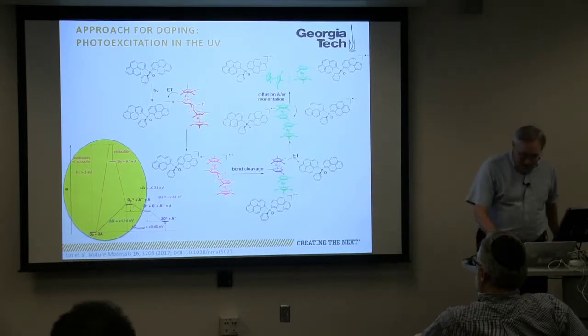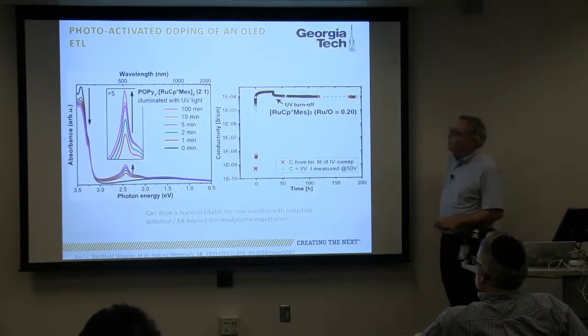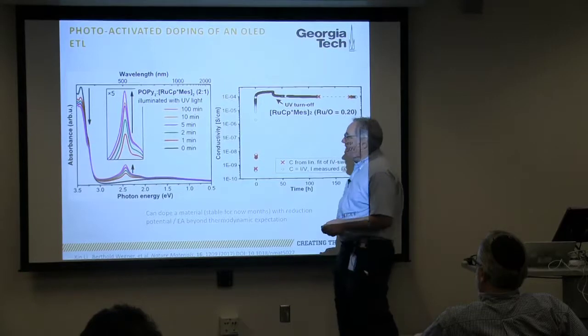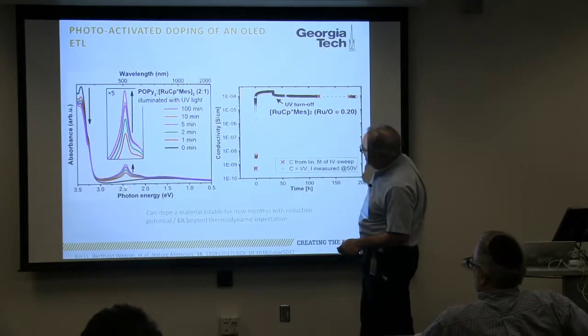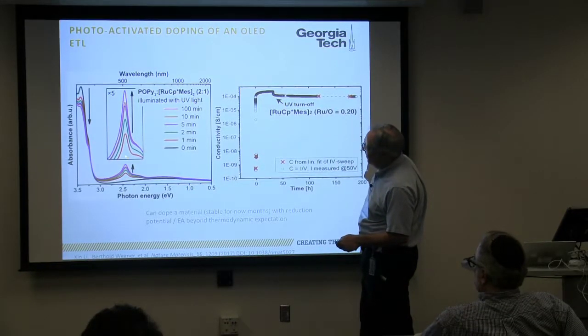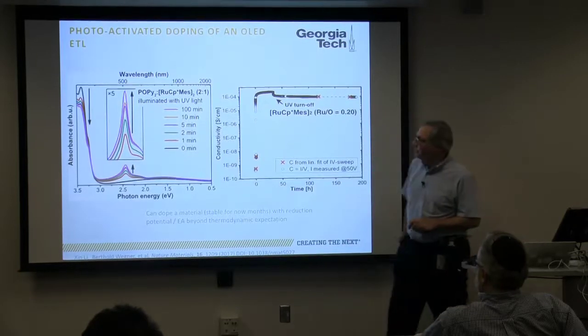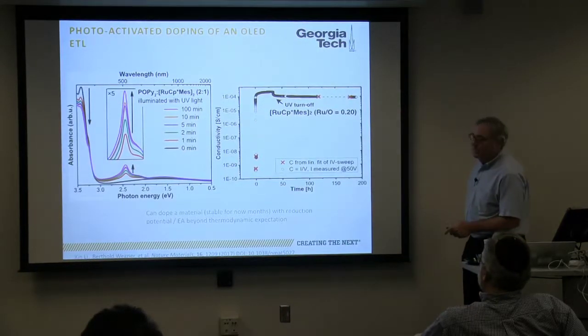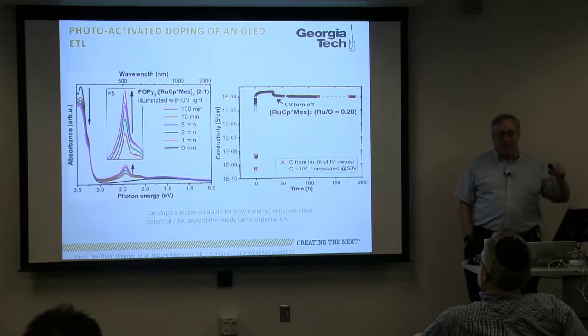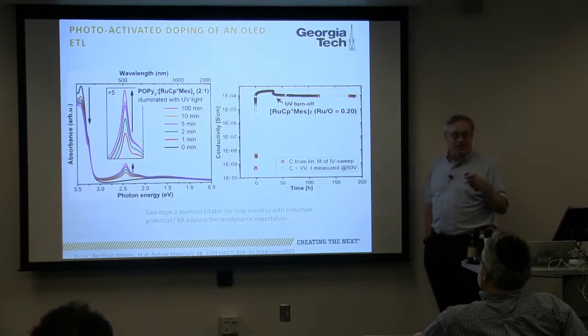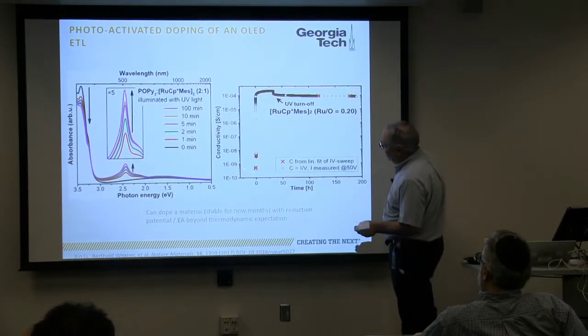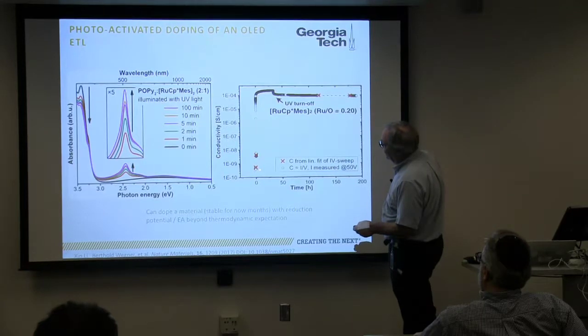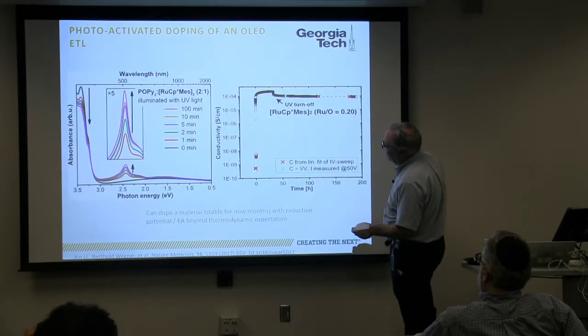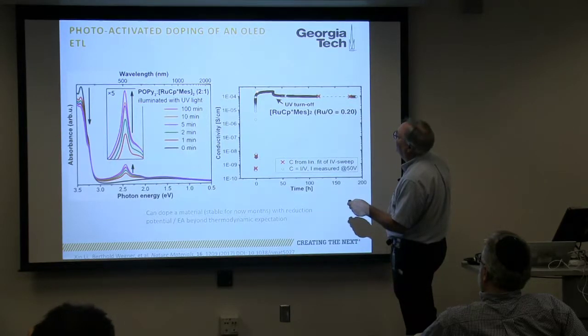Now, here's a UV-vis, an ultraviolet-visible spectrum, showing this. And this peak here is that anion growing in. We know it, trust me. Now, here's the interesting thing. I told you that that reaction was uphill by 0.4 of a volt. So we turn on the light, and it goes from a conductivity of 10 to the minus 9 or 10 to the minus 10 Siemens per centimeter up to a few times 10 to the minus 3.